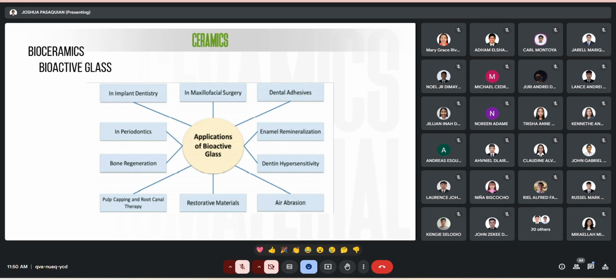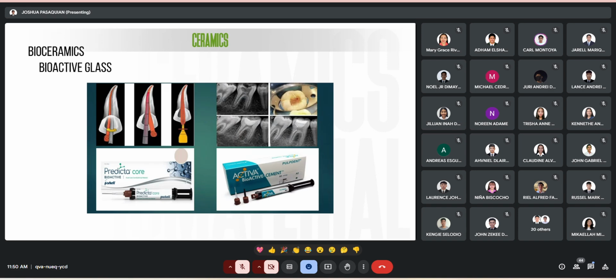Also, bioactive glass was incorporated into GIC in an attempt to produce a cement with the mechanical characteristics of a resin composite and the antimicrobial properties of GIC. It was proved later that bioactive glass enforced GIC has a higher flexural strength than regular GIC, but this experiment was of little success, since it was found that the other mechanical properties were actually compromised. Therefore, this application of bioactive glass is only advised in low-stress situations. Bioactive glass can also be used in pulp capping and root canal treatments.